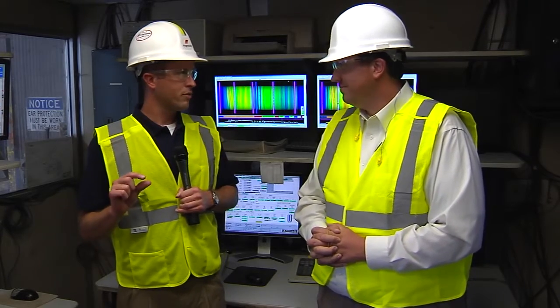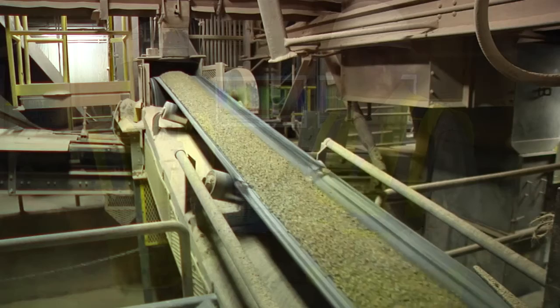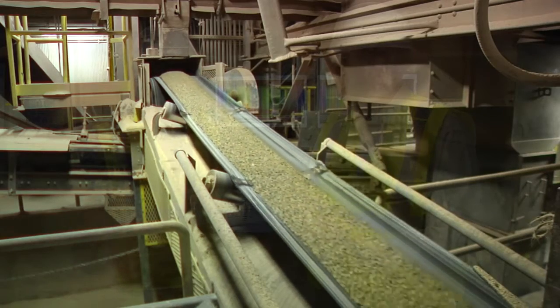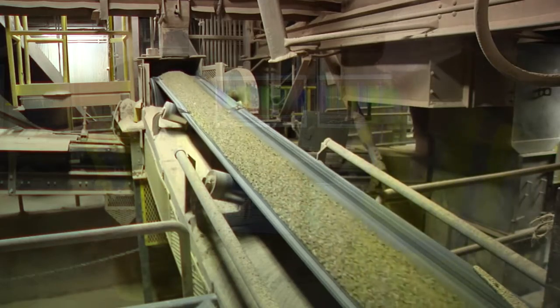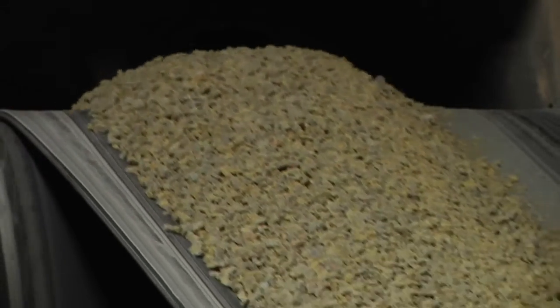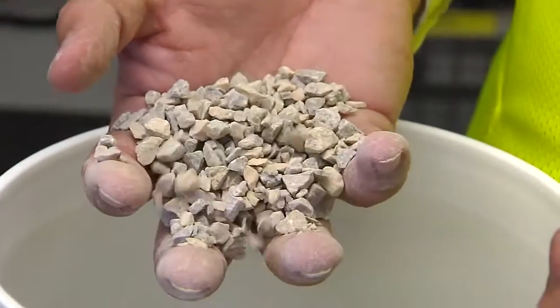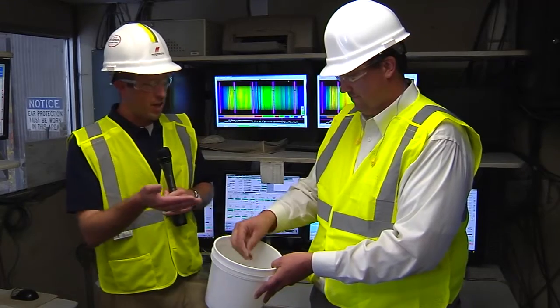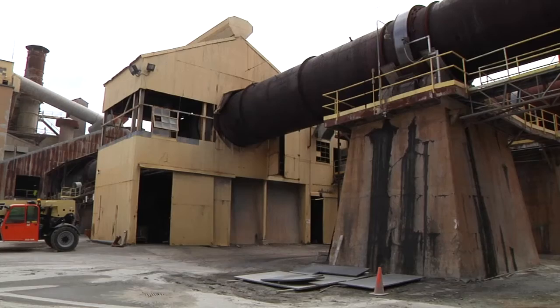That's correct. It's very special, with very low impurity levels and high density, which is very critical for making a refractory product that will withstand the high temperatures of steel making and cement and lime and other processes that it is used in. After it is mined out of the quarry, it's crushed down to about a 2.5-inch size, crushed again to about a 1/4-inch size, and the fines are screened to this feed size that you see here. This size feed is introduced to the kilns.